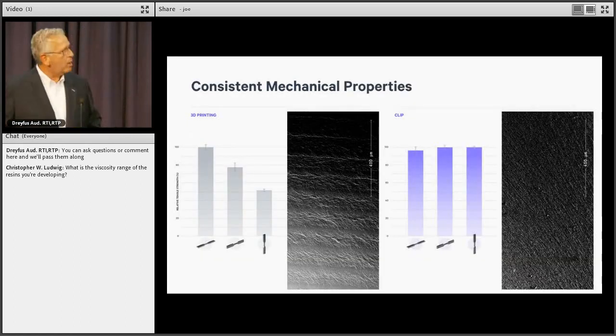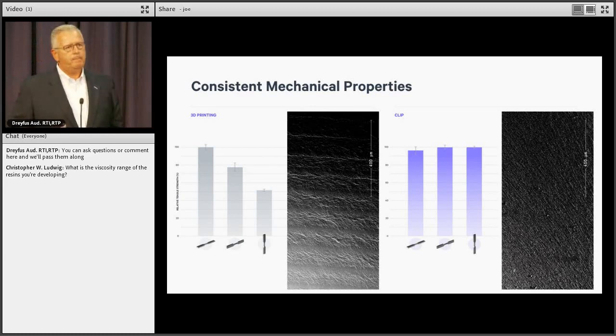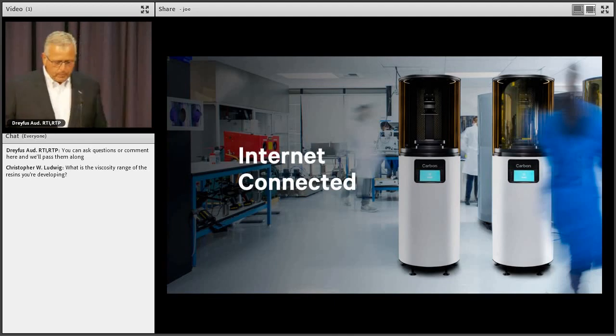And if you cleave our parts, a traditional 3D printed part made using a classic light-based SLA technology, 2D layer by layer, if you cleave a part, what you'll see is the layers derived from the traditional building up of a 3D part, and the mechanical properties depend on the orientation of those layers, as you'd expect. There's anisotropy due to the layering of the chemistry. But when we grow parts, we can't detect these kinds of layers, and you can get isotropic parts, especially the kinds of engineering resins that we use give rise to materials that are isotropic, which is really, really important for a whole host of applications. So that's the technology, and we've put it together into an amazing complete offering here.